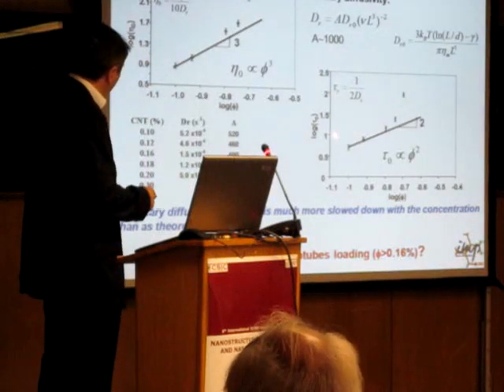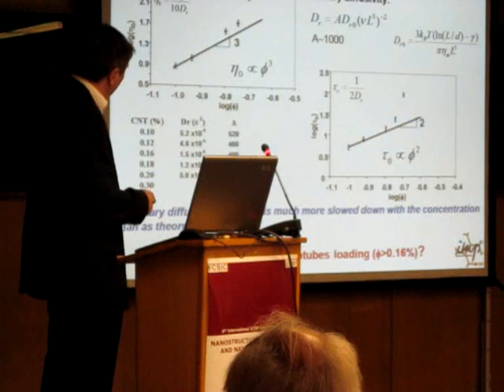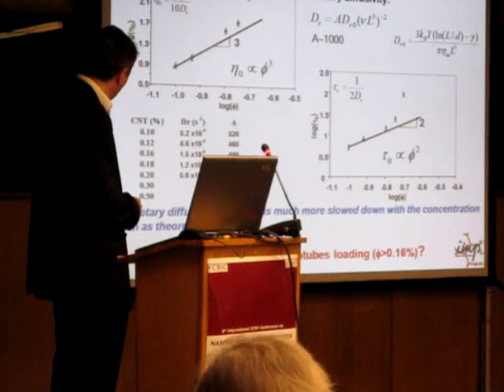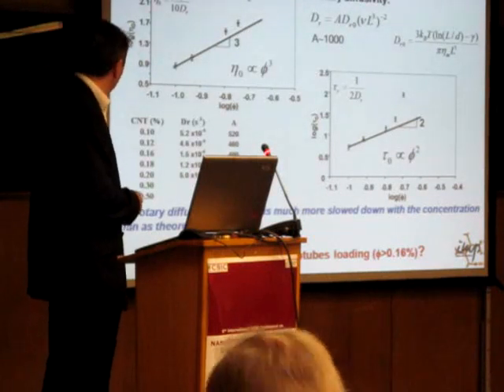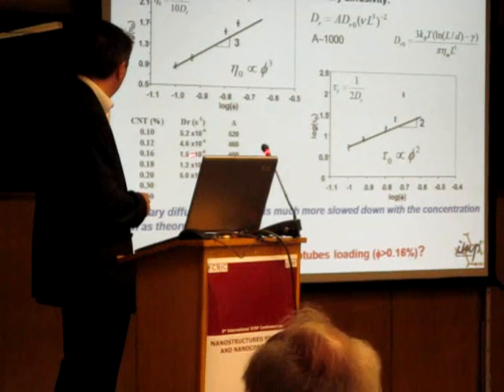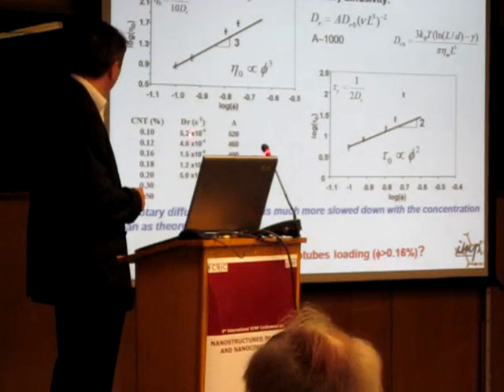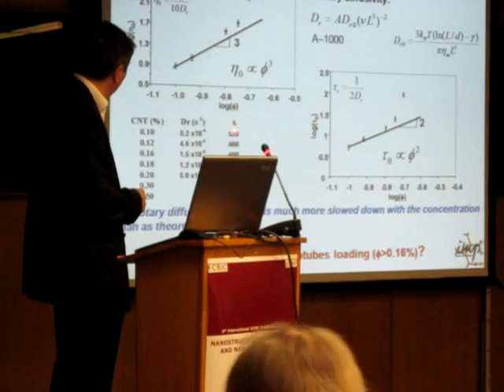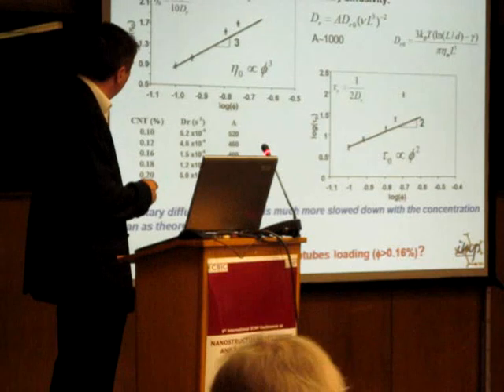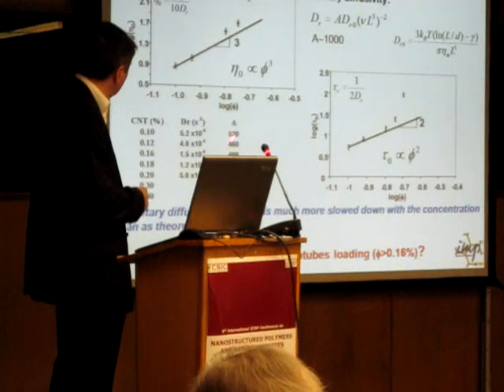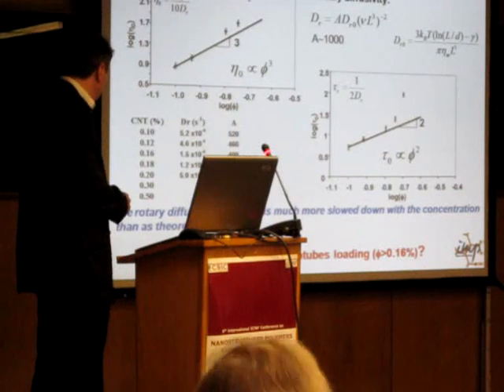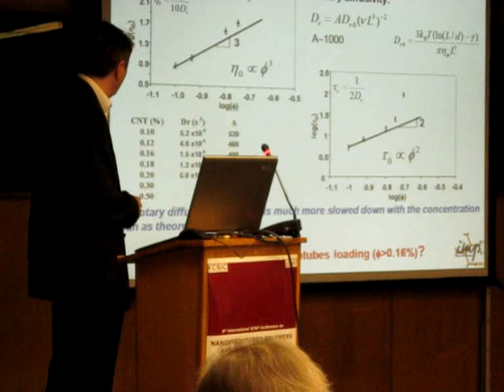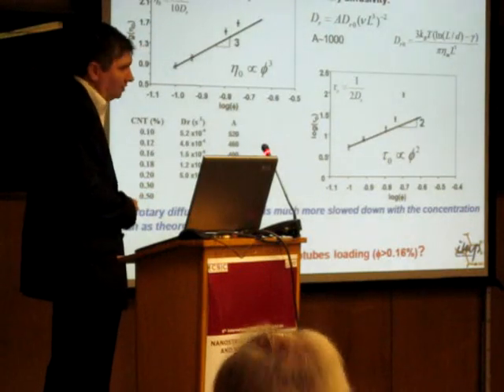And you have the same thing for the relaxation time. And from the size of nanotube and the aspect ratio, we can calculate the rotary diffusion. And from the rotary diffusion, we can calculate the factor A, which is in this equation. And the decrease of this factor means that the rotary diffusion of the nanotube is much more slowed down with concentration than theoretically speaking.